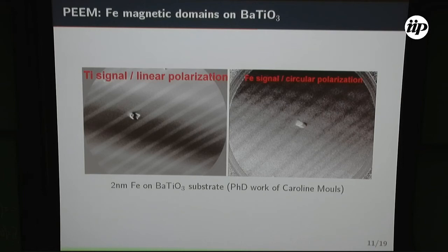So microscopy, and you can, at the same time, tune into the titanium, measuring the linear polarization, titanium edge, ferroelectric domains; tune into the iron, circular polarization, iron edge, magnetic domains. And we have measured a few regions. It's very interesting results here.